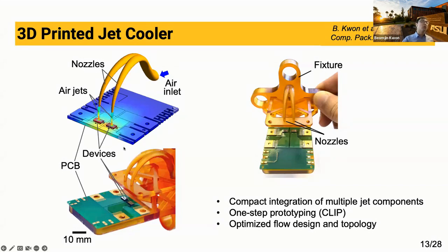So what we did was optimize the flow passage of the jet nozzle. So we gradually shrink the flow passage from the original flow supply to the final nozzle exit, which reduces the pressure drop due to abrupt change of flow passages. And also we optimize the nozzle diameter and the spacing between the device to the nozzle exit. So all those parameters are very critical in the jet cooling performance. So we optimize those parameters through numerical simulation, and then we were able to 3D print this system.